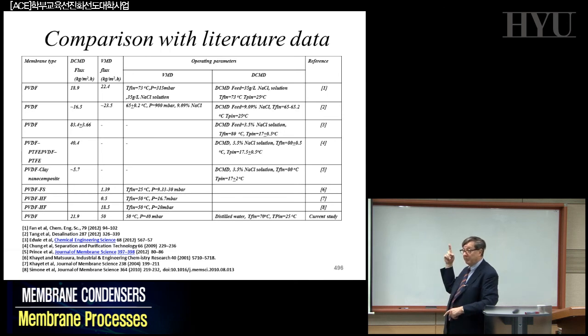Otherwise, you learned that with big pore size there will be no hydrophobic character, because the Laplace equation tells you that if the pore size is too high, there will be liquid penetration with just a few millimeters of water pressure applied. So if you have a clear idea in mind of what you're looking for, you can today try to realize, with the new polymers, the appropriate configuration for the expected result. And in the end, you make membranes which are better than all the other membranes around, not by heart, but by understanding all the mechanisms that control the final morphology of the system for the specific application.